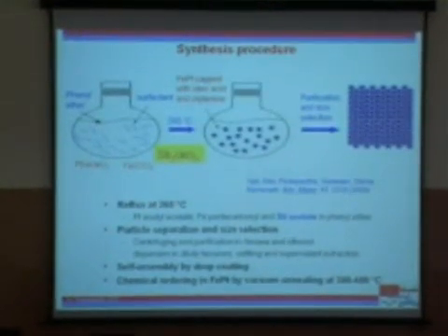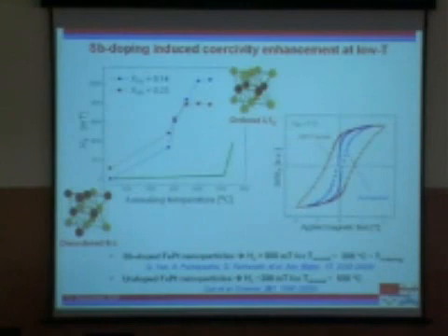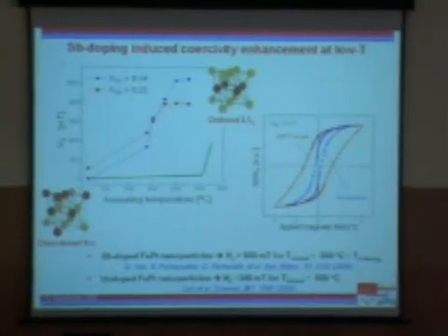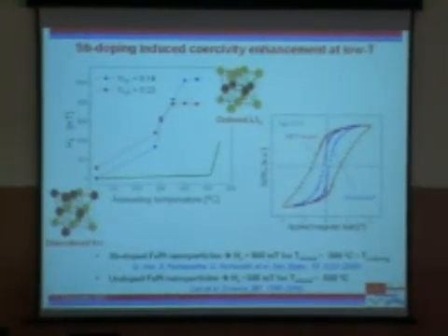So we took a couple of approaches, one not very successful and one extremely successful. I want to just share with you both of those. I won't bother you with the details of the chemistry here. Just want to say that we take platinum and iron and we put in this additional element, antimony. The idea was to get the ordering, or the crystal structure, that gives the high coercivity phase at a lower temperature, so that we don't go to high temperatures which would destroy the architecture.